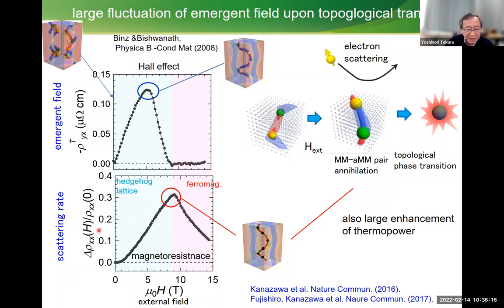And another one is, we just measured only the longitudinal magnetoresistance. Usually the compound is almost ferromagnetic, so the magnetic field always reduces resistivity. As you may know, this is the case of the colossal magnetoresistance. But in this case, very surprisingly, when we apply the magnetic field, resistivity tends to increase. At the phase boundary, it reaches the maximum, then goes down.